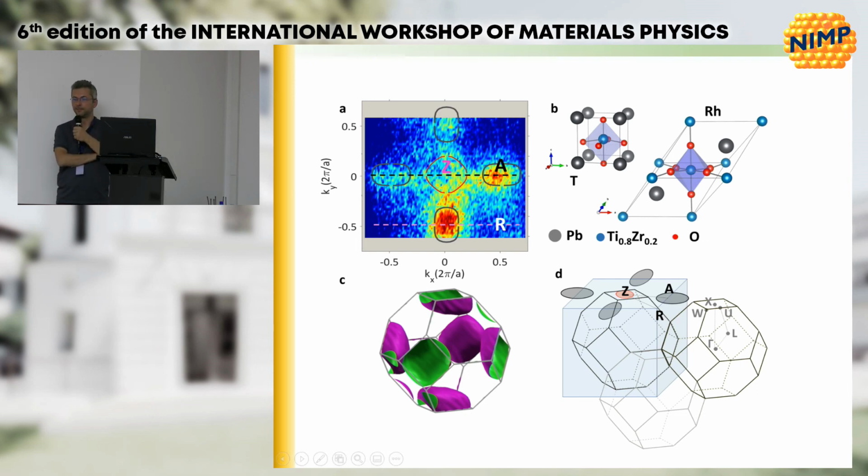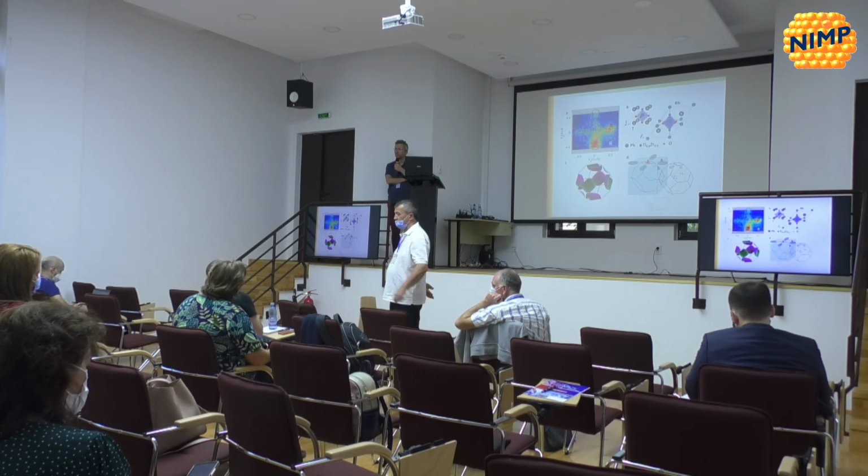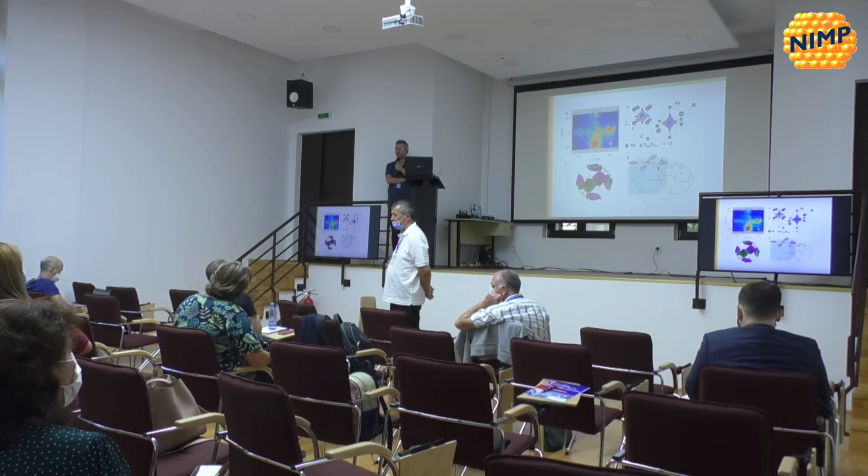So your rhombohedral cell, that your film inherits from the substrate, includes tilts, presumably, of the octahedra and all that, right? So isn't there any evidence before your ARPES data of whether that happens in PZT grown on LSMO? Because this must be a film that has been looked at by X-rays, and this kind of doubling of the unit cell should in principle show up, I would imagine, in some experiment.